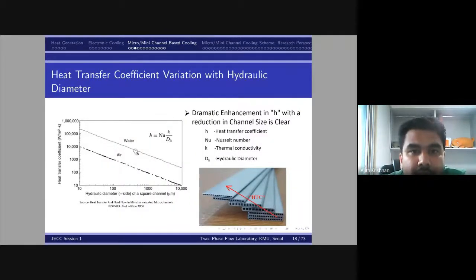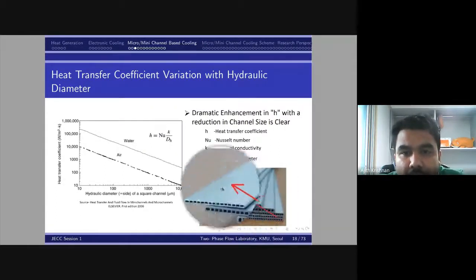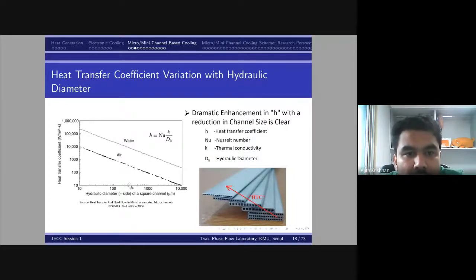So this is the heat transfer coefficient variation with the hydraulic diameter. If we go from a bigger channel size to a smaller channel size, you can see here what the increment in the heat transfer coefficient is when we reduce the channel size. There is a drastic increment in the heat transfer coefficient. Initially it was nearly 10, and later it has increased to 10,000 for a 10 micrometer hydraulic diameter unit. So with the reduction in the hydraulic diameter, definitely there is an increase in the heat transfer coefficient due to the increase in the surface area density.